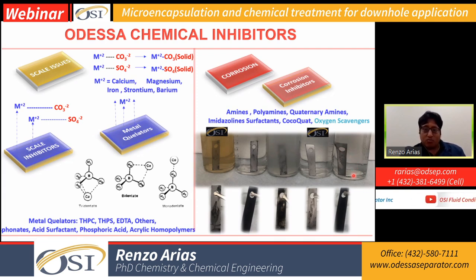You can see that after one day, the whole coupon has been covered with iron sulfide because it doesn't have any corrosion inhibitor. That's what will happen with your pipes. See the examples with the Odessa Separator chemicals: the formation of iron sulfide has been reduced by almost 80%. See other chemical inhibitors, they don't have the same effect.